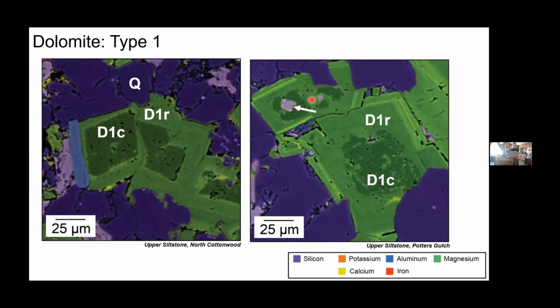In most cases, these rims, or these dolomite cores, type 1 dolomite cores, are found precipitating on detrital feldspar grains or remnants of detrital feldspar grains. Again, suggesting these are a later stage than that feldspar dissolution. And in many cases, this abundance of feldspar within the dolomite crystal itself results in that cloudy appearance of the cores in thin section that I showed on the last slide. So it makes it easy to recognize the cores from the rims in thin section.